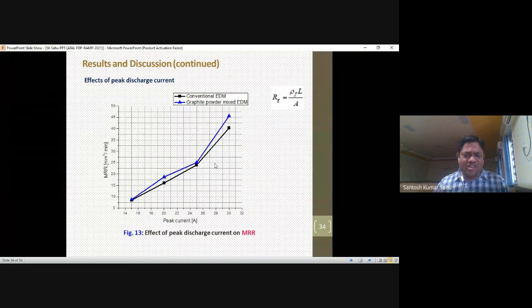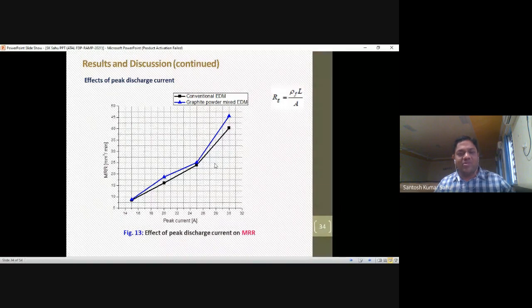So again, by adding the graphite powder, there is some bridging effect that causes some interlocking among these powder particles, and thus they behave like a chain under the sparking area. So the sparking intensity is remarkably increased within a discharge, leading to a faster erosion from the work surface and consequently improving the MRR also. That's why this MRR is a little bit increased with the help of the graphite powders.